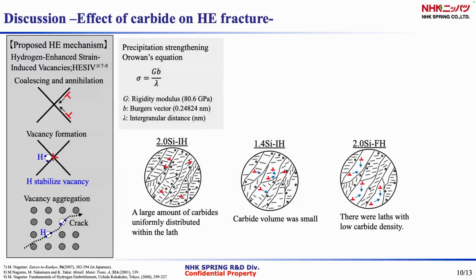We consider how the carbides and retained austenite affect hydrogen embrittlement. I will explain the carbides first. The HESIV theory assumed the generation and annihilation of dislocations and hydrogen trapping in vacancies, resulting in vacancy aggregation and fracture. So it is important to suppress dislocation motion in order to prevent hydrogen embrittlement. The resistance to dislocation movement is expressed by Orowan's equation, and the amount of precipitation strengthening increases as the carbide distance decreases.